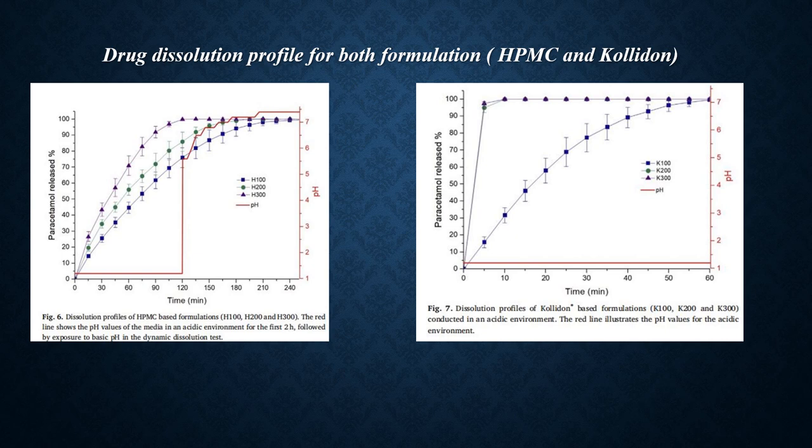From Figures 6 and 7, the drug dissolution profiles for both formulations are shown. For the HPMC formulation, increasing laser speed affects the drug release rate from 100 to 300 mm/s. For the H100 formulation, processed at 100 mm/s, the time for complete paracetamol release is 4 hours. For the H200 formulation at 200 mm/s, it released at almost 3 hours. For the H300 formulation at 300 mm/s, the fastest dissolution profile was achieved at almost 2 hours.